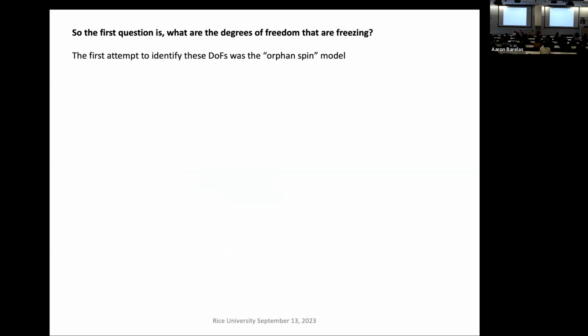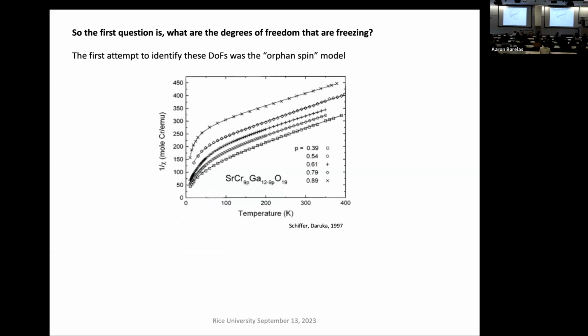The first question is, what are the degrees of freedom? The first attempt to identify the degrees of freedom was the so-called orphan spin model, which was a very simple idea promoted by my former postdoc, Peter Schiffer, right after he left me. And it makes sense. Just looking at the data, you can see that it looks like a line plus a deviation. So you model that since this is inverse chi, that deviation has been added, an added part of the susceptibility. So why not call that added part a set of spins, calling them orphan spins? Spins that are not, for some reason, connected to the rest of the spins. So you write 1 over chi as a sum of two, you write chi as a sum of two independent contributions, orphans and background spins. And you assume they're independent.